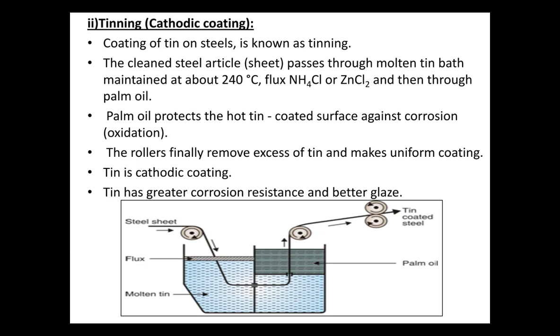That means when we coat a steel article with tin and if they come in contact with a conducting medium, then tin will act as a cathode and steel will act as an anode. But since the coating is there, tin will protect the steel from corrosion. But again, if the film of tin which we have applied on steel gets ruptured, then steel will also come in contact with the conducting medium. In that case, the base metal will undergo corrosion acting as an anode and the coating metal will act as a cathode. So this is less preferred as compared to galvanizing, because galvanizing is an example of anodic coating and tinning is an example of cathodic coating.